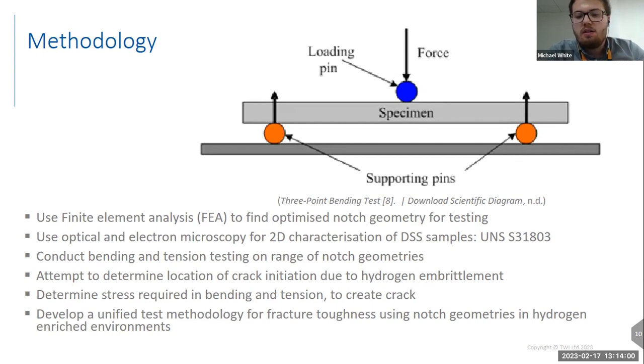Once physical testing of the duplex stainless steel begins, optical and electron microscopy will be used for 2D characterization of our metal specimens. The location of crack initiation and the stress required to initiate the crack formation will be determined using acoustic emissions testing. The ultimate aim of our project will be to create a unified testing methodology for fracture toughness in hydrogen-enriched environments.